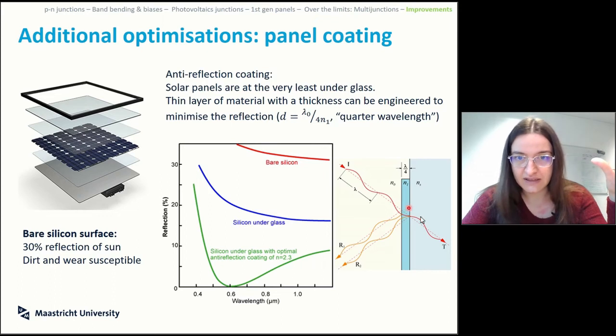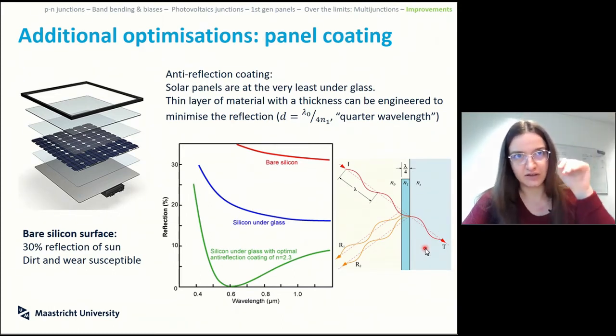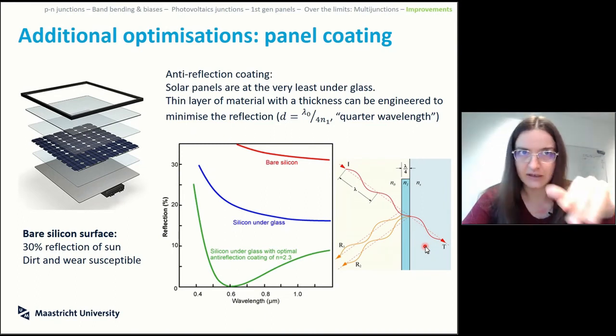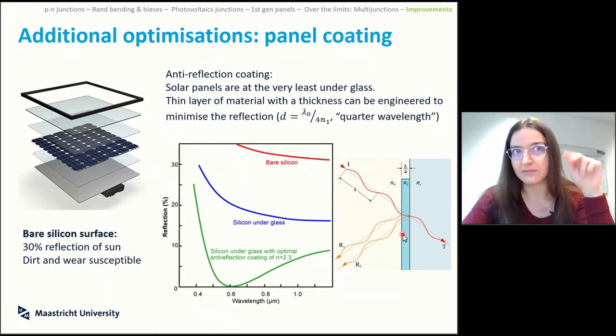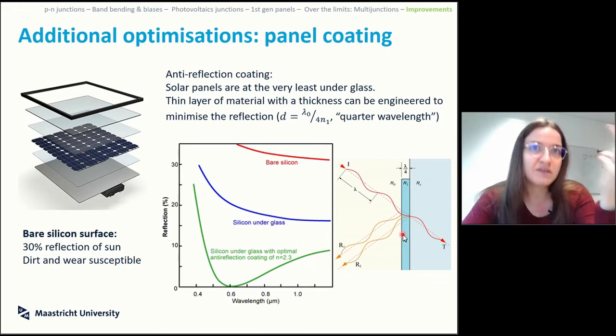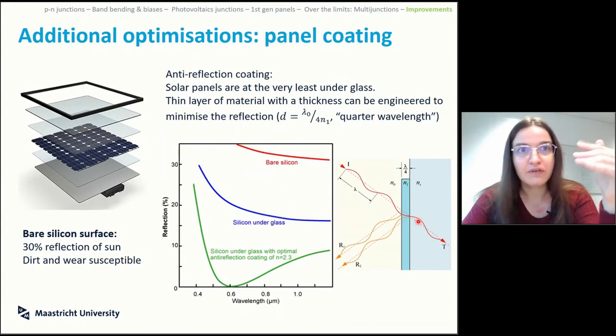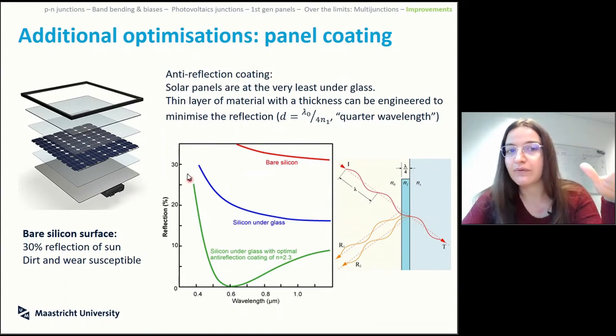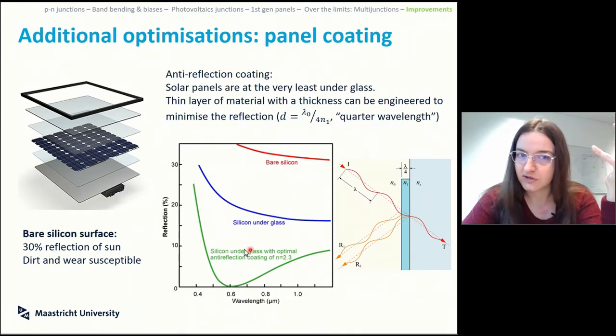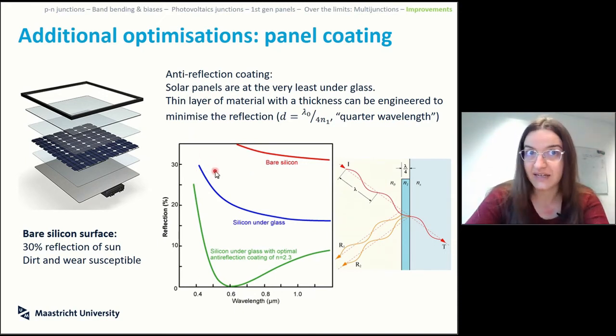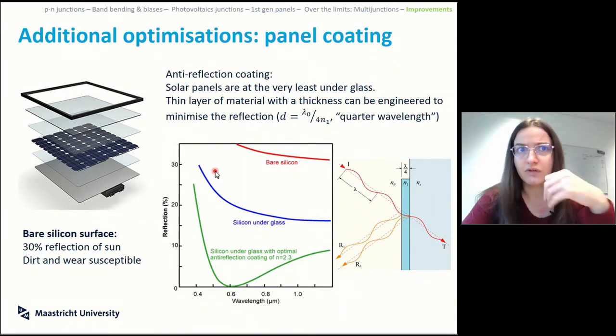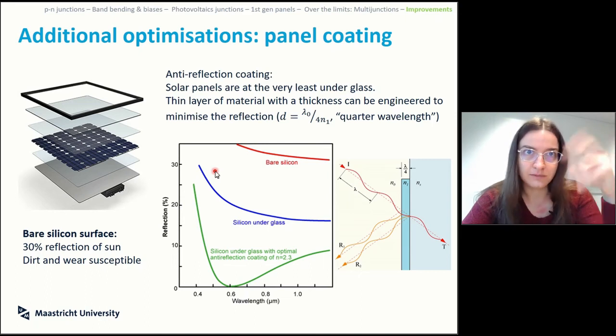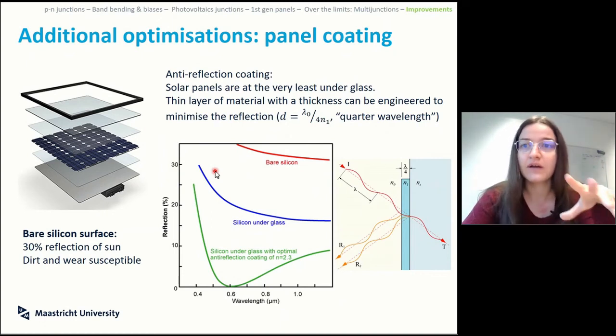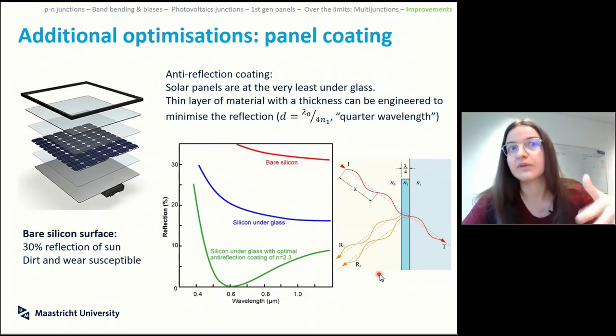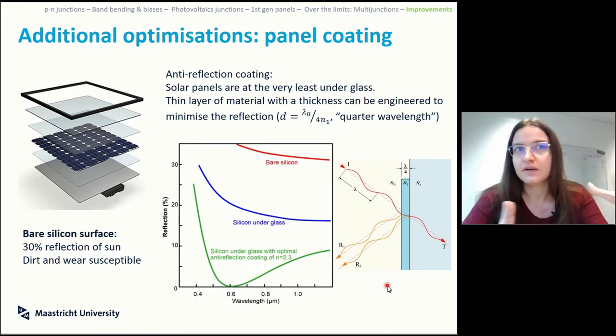The reflection works with where you are touching your glass and how thick your glass is, with a certain refractive index. And depending on where you touch your wavelength in terms of interference, you get reflected off with a certain percentage or not. What you want is the perfect transmittance for the right wavelength, and you can see that it cannot be perfect for every wavelength. Even when you optimize the anti-reflection coating, you still see a huge reflectance of other sunlight. This is not necessarily bad, because you might want to reflect off any sunlight that you're not going to use for your solar panel, because anything that your solar panel gets hit with and does not absorb results in heat. So this is already a nice optimization that lets us work through a lot of stuff.